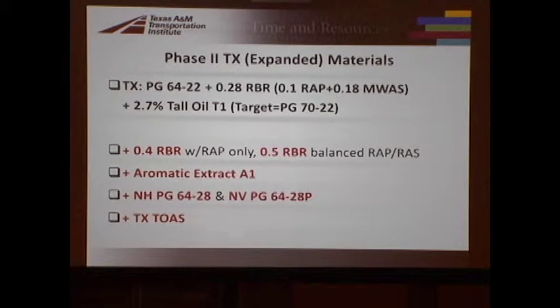So the initial phase 2, before we went to the panel meeting, we looked at a field project constructed in Texas in 2014, where we were lucky that as this project was starting, there was a Texas project being utilized on a TxDOT research project, and it used a 64-22. The target binder was a 70-22, but when they add in RAP and RAS, a lot of times, by the TxDOT specifications, you do a substitute binder and you lower the high temperature grade. So we have a PG 64-22.